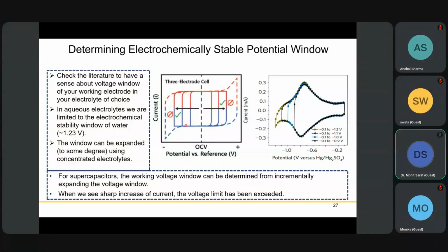It is also very important before beginning any experiment to determine the electrochemically stable potential window. If you have a completely new material, you have to do a lot of optimization. But if your material is already reported and you are studying it in a different electrolyte, it is always advisable to check the literature first and get a sense of your voltage window.